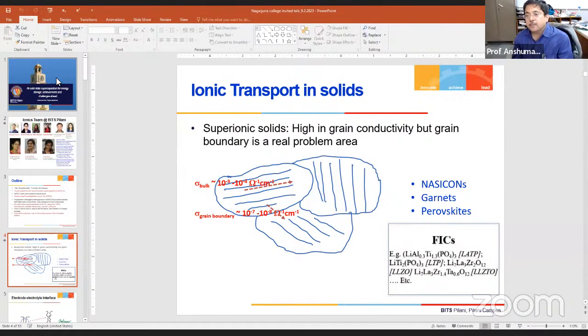But then it is about the grain boundary, again the solid-solid interface. When one grain and another grain are in contact, they exhibit poor conductivity. As long as the ion moves inside a grain, it is very comfortable to give high conductivity. So the bulk conductivity of these developed ionic compounds is very high. But when you cross the interface, you lose the conductivity because of the high grain boundary impedance. That is the biggest problem for the application of ionic solids in real energy devices, because if you have large grain boundary impedance, we cannot achieve high conductivity.